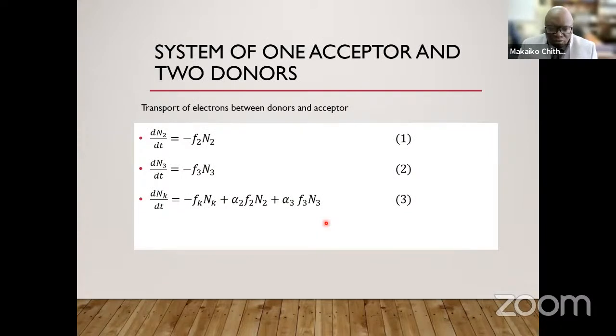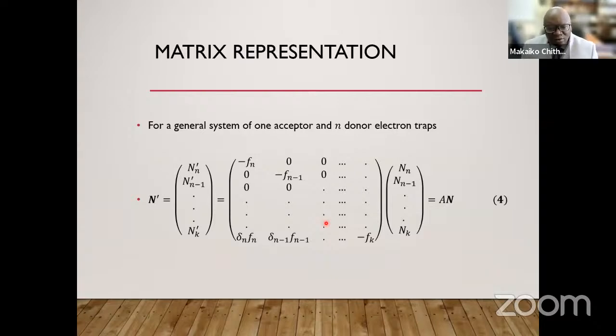Now, a more convenient way to express this, because remember, you can't always know the number of donors in your sample. If a sample is well behaved, you can guess, but in reality, it's difficult. So sometimes it's more convenient to express this as a matrix. If you have a general system of 1 acceptor and N donors, then the transfer of electrons from donors to an acceptor can be written more compactly, as I've done here in equation 4.